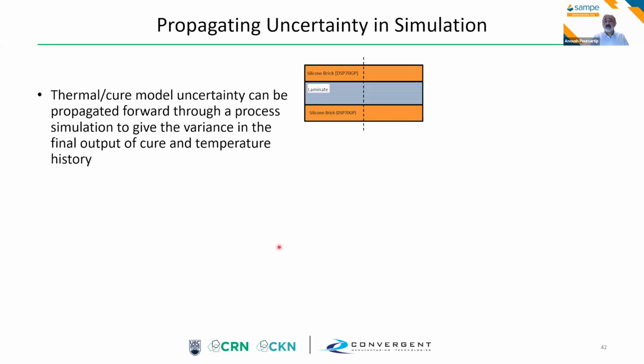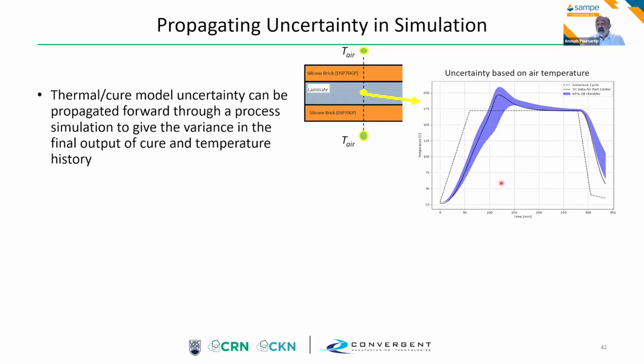Let's look at a very simple example. I'm going to take a laminate. I'm going to encapsulate it in silicone so that I get huge thermal lags through the thickness. And I'm going to control the air temperature. And I'm going to ask myself, what's happening to the temperature in the middle of that laminate? The answer is that you can actually, well, in this case, I'm actually showing the true TC data, but you could predict that. And if you actually feed into that your uncertainty with your heat transfer coefficients, your material model, what you would actually get is this blue profile.